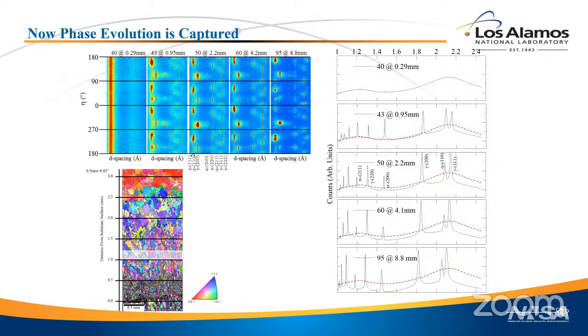So the sharp peaks of the diffraction, the two sharp peaks up here, this peak is austenite, this peak is ferrite. Okay, so it's more complicated than that, but we'll get the fractions of the austenite and ferrite by the ratios of those and the other peaks. But as you come down, you can see how we get less and less broad scattering. So you're getting less and less amount of liquid as you move away from the melt pool.